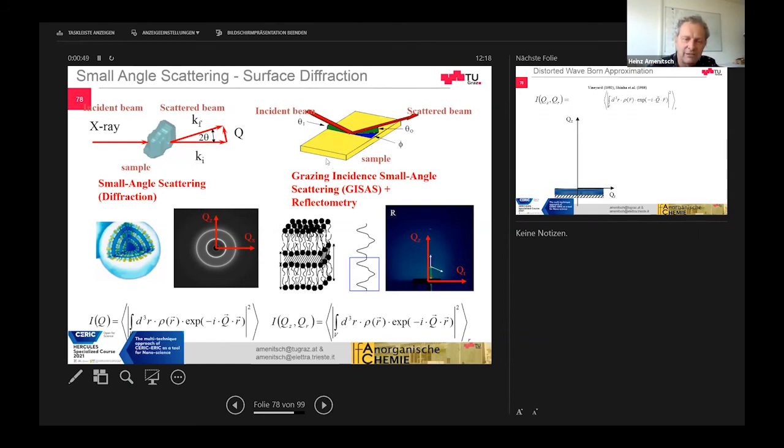If you look now at surfaces, you have these elongated planar structures, so they self-assemble and reorder themselves on the surface. And you're not getting these diffraction rings anymore, like in powder diffraction, but you get diffraction peaks due to the one-dimensional alignment in the out-of-plane direction, and also in the in-plane direction if you have in-plane order, and this would be the out-of-plane order.